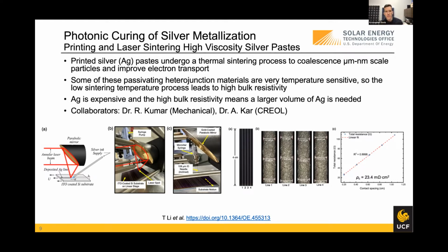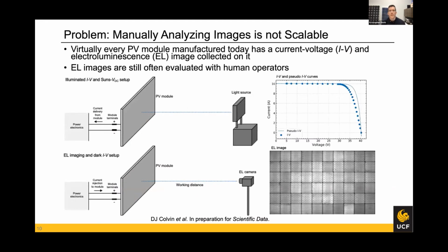So we've been looking at using laser sintering as a means to only sinter the metal contacts. And essentially the wavelength that we use is transparent to the other layers, so they don't absorb light, they don't heat up. It's just the metal that heats up. And what we've been able to show is that this technique can actually lower the bulk resistivity of these silver contacts quite a bit, allowing you to use less silver, saving money. And now what we're interested in is, can we actually do this with copper? Because the DOE in particular is very interested in moving away from silver to copper because of the costs associated with silver.